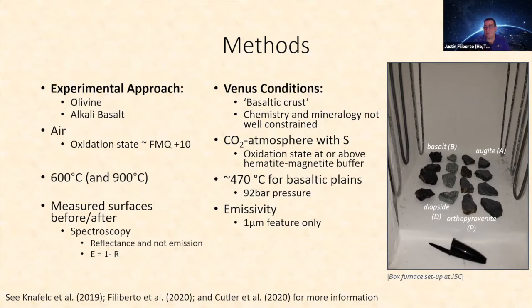Our experiments were done at 600 degrees and 900 versus 470 for basaltic plains and 92 bars. 470 versus 600 should not make a large difference, although this will speed things up a little bit. 900 degrees obviously will speed things up, and this was only done for the olivine. We measured the surfaces before and after for spectroscopy, and this is directly relevant. However, we have full spectroscopy, and for Venus right now, we're really only focusing on the 1 micron feature. And so I'll point out where the 1 micron feature is on my graphs.